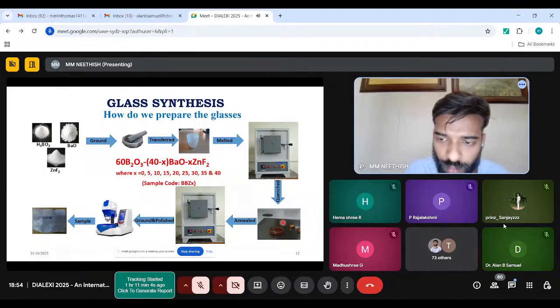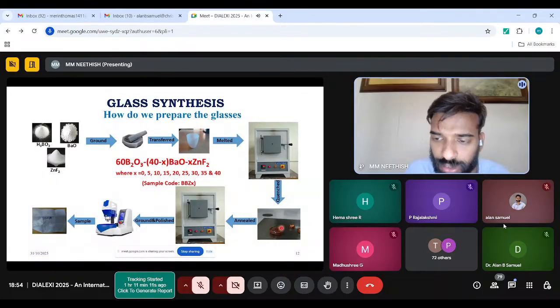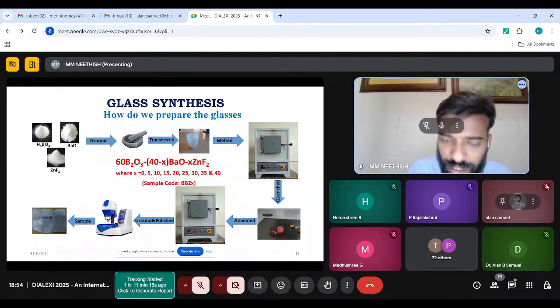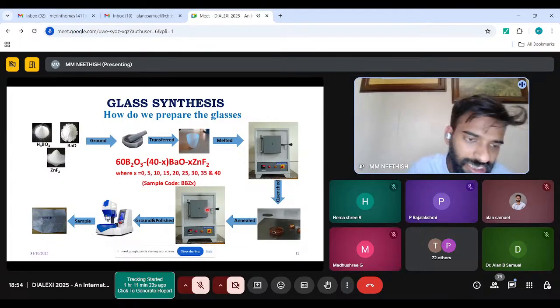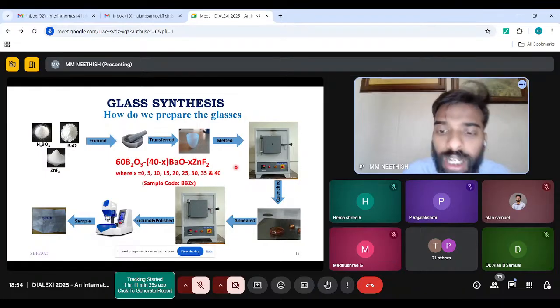So once you get these glasses, the problem is that you will have a lot of stress when you quench to room temperature. So you have to get rid of the stress. To do that, you have to anneal it. You keep it in the furnace not at a very high temperature, but a very low temperature, which is below the glass transition.